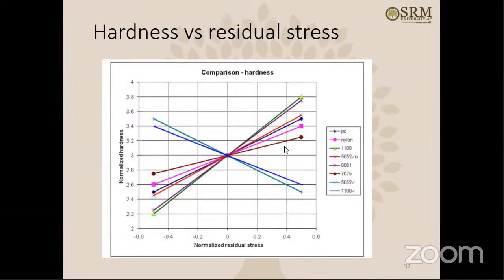This is the experimental result actually. The experimental result shows that as the residual stresses in the material vary, some plots are going from the left side to the right side and increasing. However, the other plots are going down, decreasing. That depends on the different materials. Which ones are going down, the softer materials are different, the harder materials are different. The softer materials are giving a different response, harder materials are giving a different response. This is what shows how the hardness varies along the residual stress.